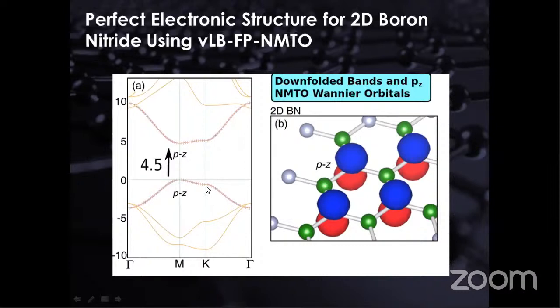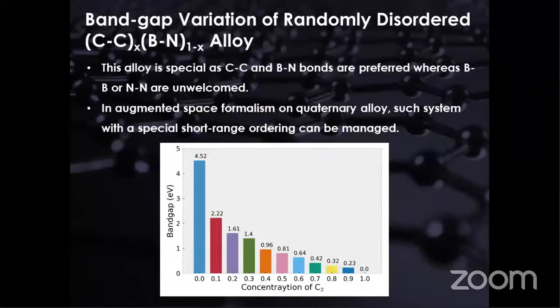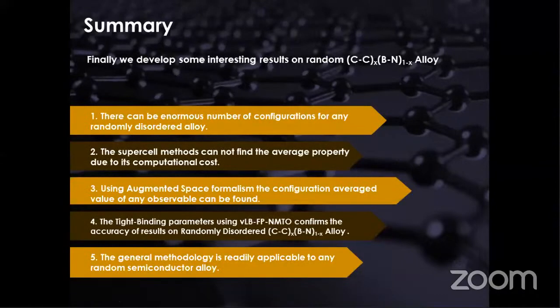Okay. The PZ bands are quite okay with the results. Using this, we can always calculate the variation of band gap for different concentrations. This particular alloy is a special alloy because the carbon-carbon and boron nitride bonds are preferred, whereas boron-boron or nitrogen-nitrogen bonds are not supported. And this is basically having some sort of short range ordering. And this is a general method which can be applied to any other alloy, quaternary alloy, basically.